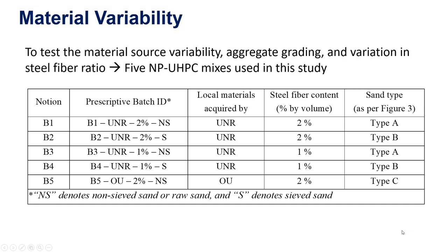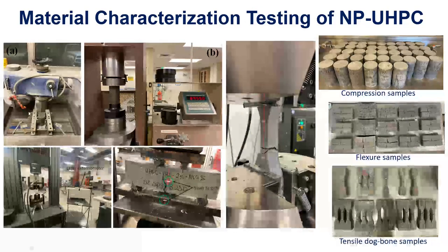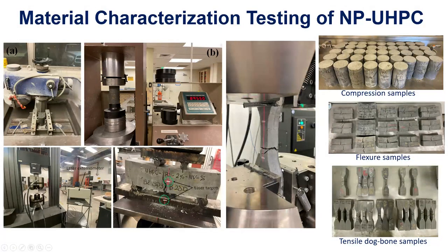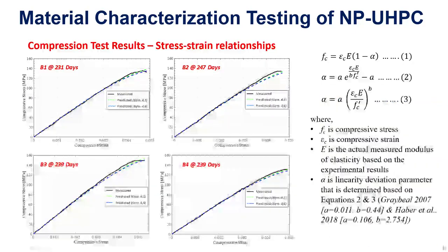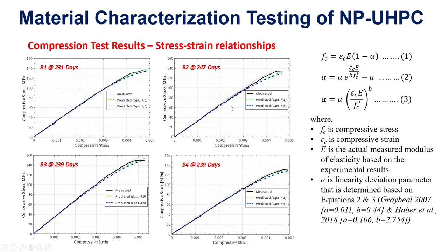We performed a full comprehensive material characterization including cylinder tests, prism tests, and direct tension tests for tensile properties. Full results are in the final report associated with this project. These samples show results from compression tests where we captured full stress-strain relationships to obtain modulus of elasticity information and compare with conventional equations in the literature for commercial UHPC.